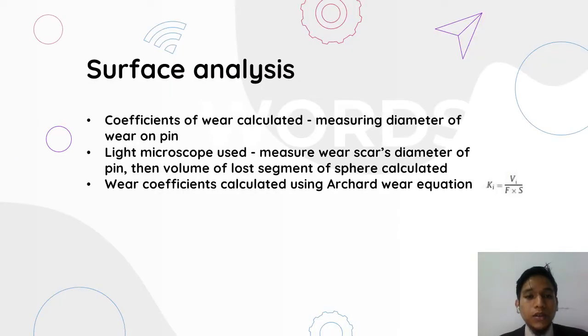Surface analysis. Coefficients of wear were calculated by measuring the diameter of wear on the pin. A light microscope was used to measure the wear scar diameter of the pin, and then the volume of the lost segment of the sphere was measured. The wear coefficients were calculated by using the Archard wear equation: K equals V over F S. F is the normal load, S is the sliding distance, V is the wear volume, and K is the dimensional wear coefficient.